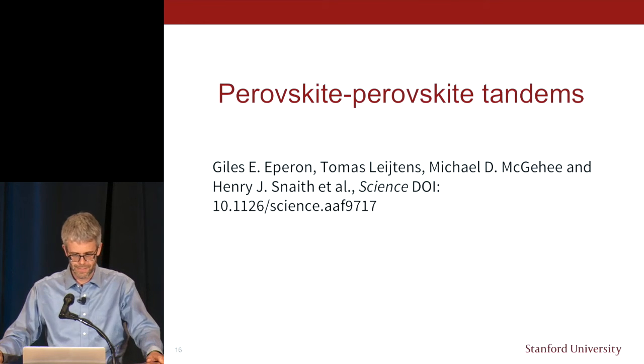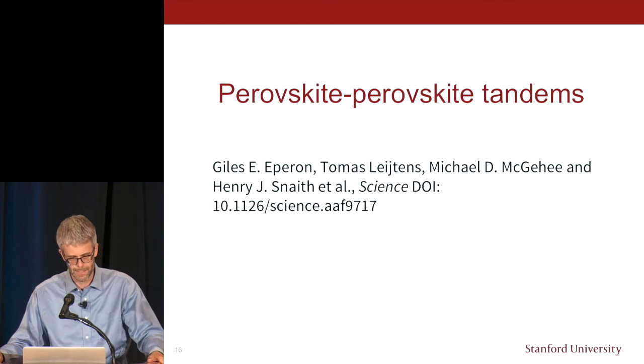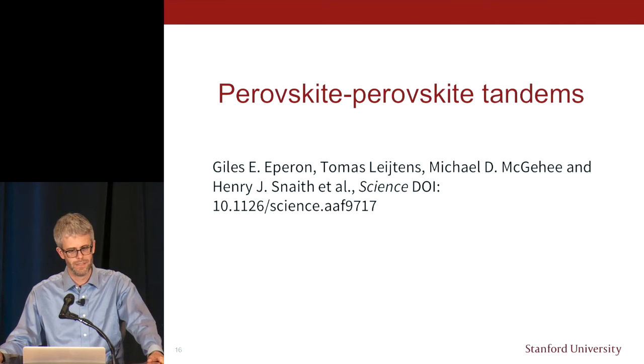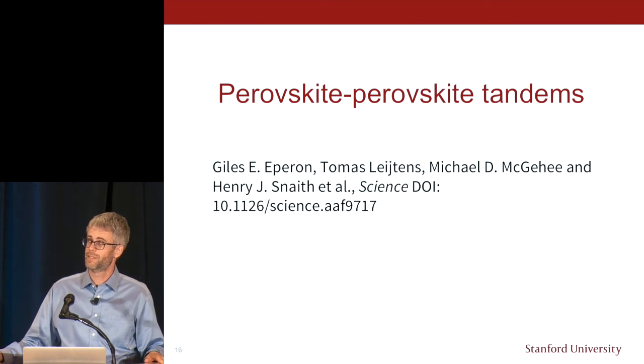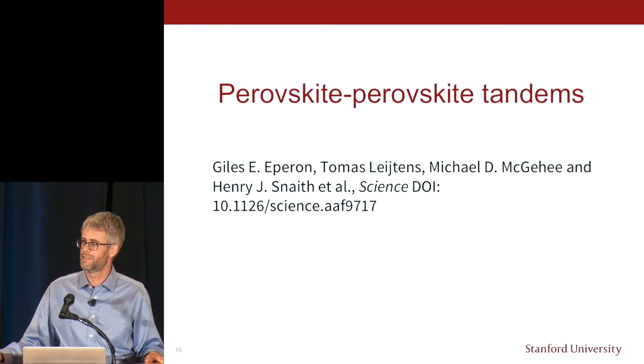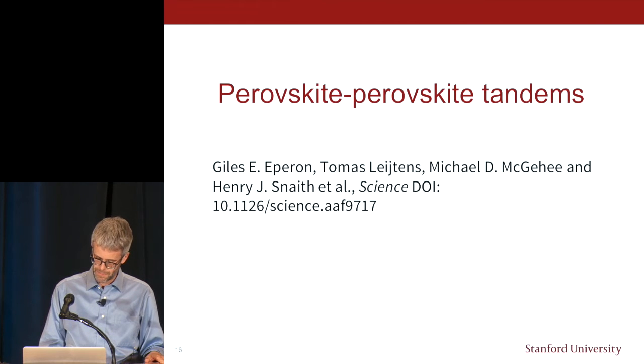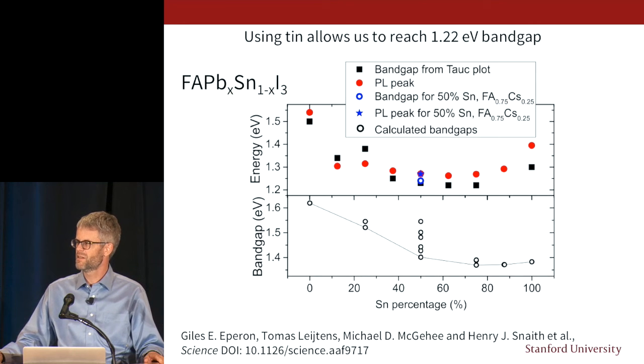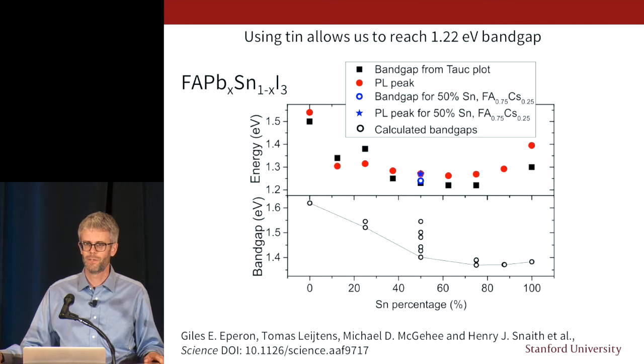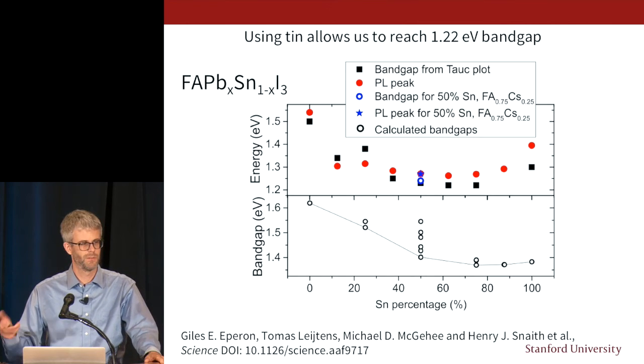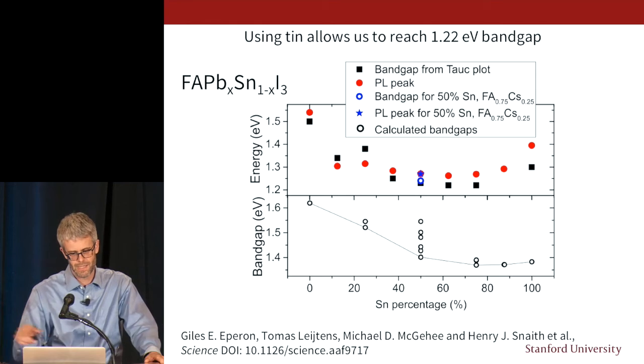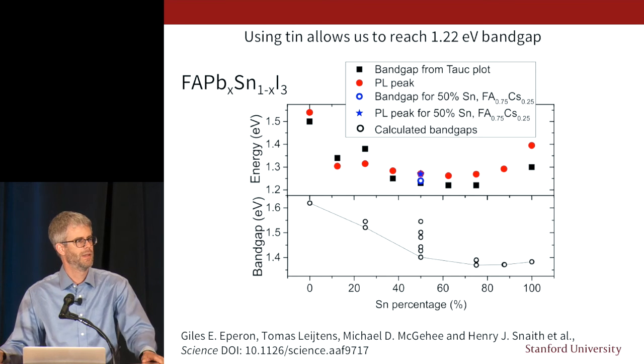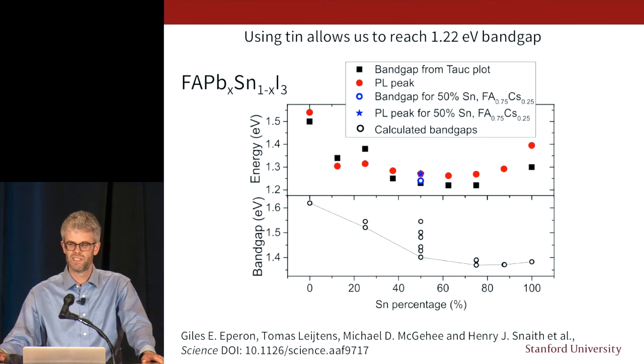So 2 weeks ago, a Science paper came out. Giles Eperon is a graduate student, or was a graduate student at Oxford with Henry Snaith, and he figured out how to get a lower band gap with tin. And Henry's a good friend, and they knew we were good at making tandems, so they sent the material over here for us to make a tandem, and we further optimized the material. Here you just see how we can adjust the band gap by adjusting the tin to lead ratio.